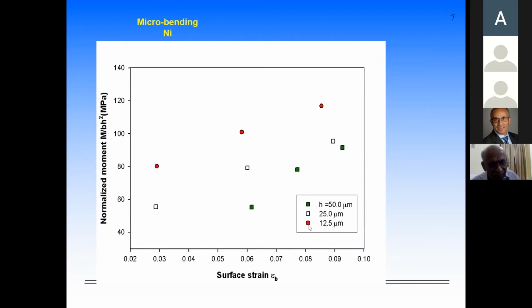So when the beam is 12.5 micrometers, you get these data points. When it is 50 micrometers, you get these data points, completely different. As a result, this has to be represented in our formulation. So that means I cannot use traditional theory of plasticity, because theory of plasticity does not have a term for the size of the sample.